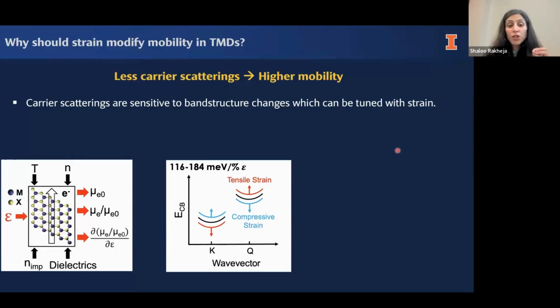A general trend of these materials is these materials have two valleys in the conduction band, meaning electrons typically want to stay in the lower energy state, but sometimes they can also get to the higher energy state. And that's what causes a lot of intervalley scatterings, and that limits the mobility of these materials. But when we apply strain, a general trend emerges. When we apply the right direction of strain, for N-type materials, if we apply tensile strain, I can move these valleys apart. If I move these valleys apart, then electrons will not have any incentive to go from one valley to the other valley. So that can increase mobility a whole lot because I'm preventing them from scattering from one valley to the other valley.